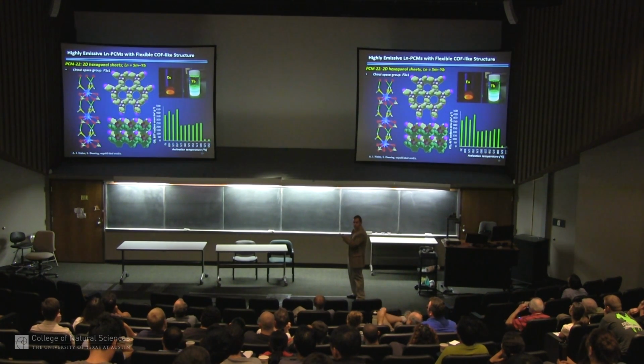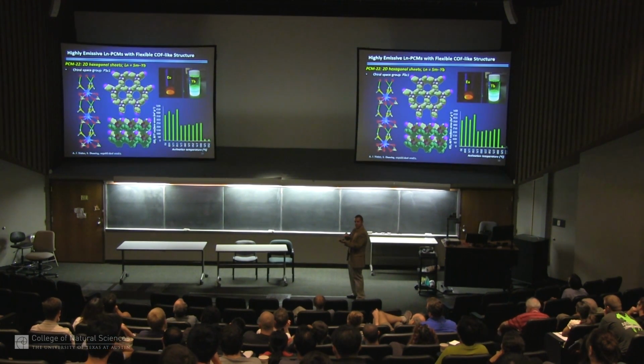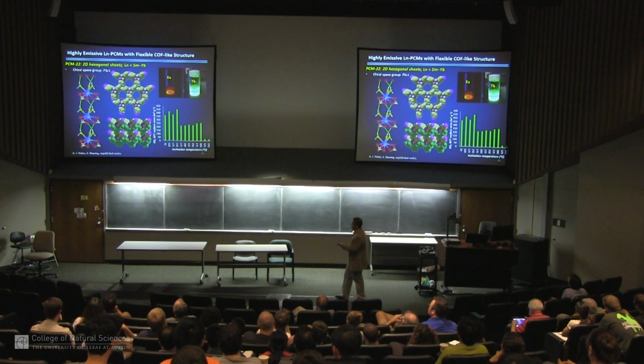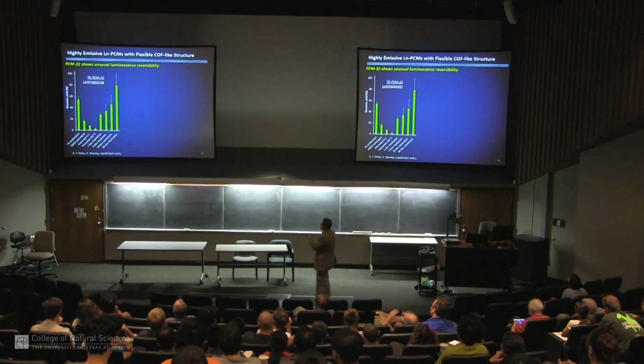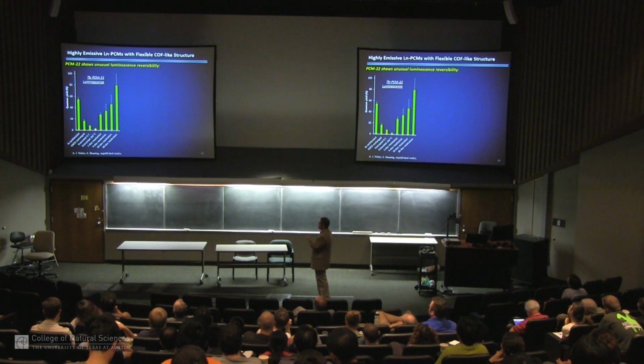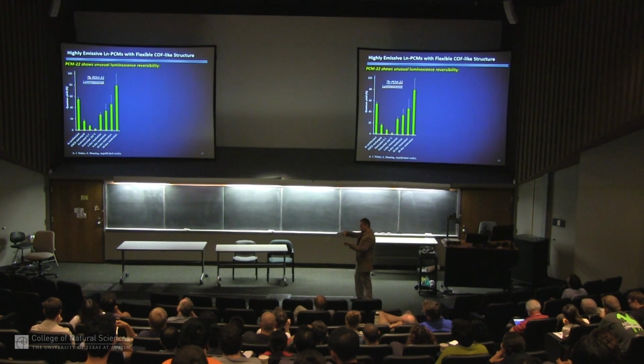Now, because I showed you on the previous slide we can remove the water, you find that when you remove these, all the layers start to shift because there's nothing now to pin them together. And you can see this in the X-ray diffraction. You can see a change in the cell parameters, and this is reversible. And we know that if we take the material and remove the solvent, everything collapses, and it looks like the material has died. There's no more luminescence. But if you expose it back to solvents, you completely recover the luminescence. So once the solvent goes back in, it forces all the layers to line up again.